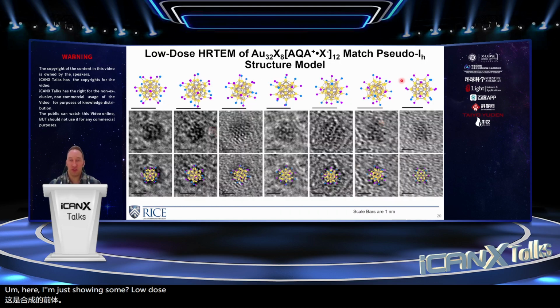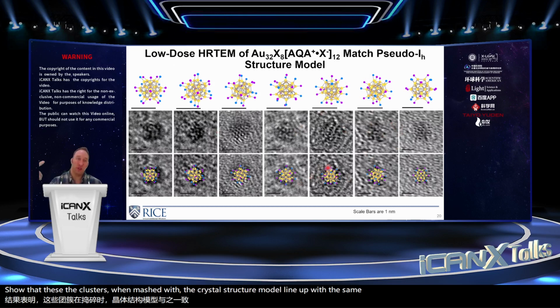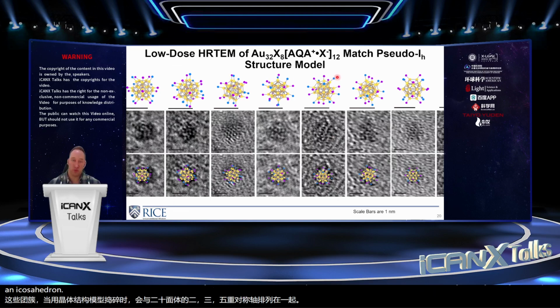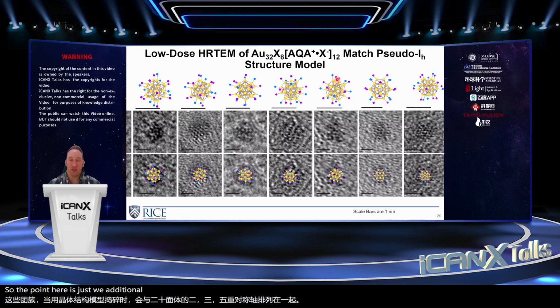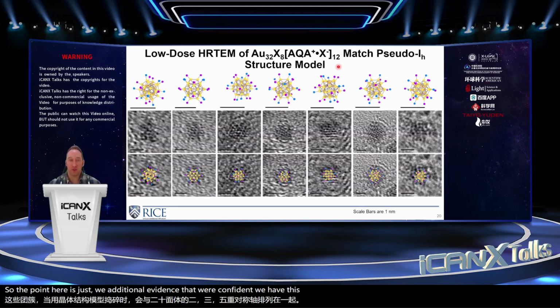Here I'm just showing some low dose TEM images that show that the clusters, when matched with the crystal structure model, line up with the same 2, 3, and 5-fold symmetry axes you'd expect from an icosahedron. So the point here is just additional evidence that we're confident we have this icosahedral structure.